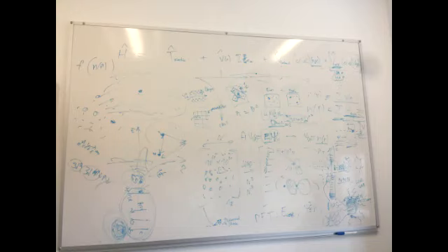Yes, and it's almost a classical simulation. So you have a set of atoms with the classical forces acting on them, except that the forces themselves are calculated based on this density. So the calculation of forces is quantum mechanical, but the movement of atoms is completely classical. So it's basically you are shaking your atoms, and if it's a solvent and nothing is attached, so a crystal doesn't have too much to shake. But if it's a liquid, this molecule can go anywhere. And then we can know like the breaking point.